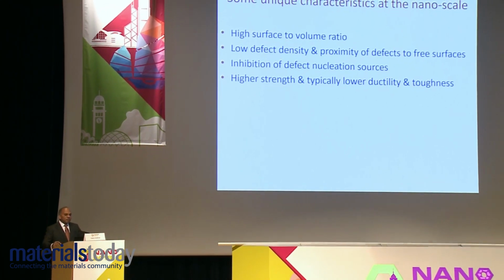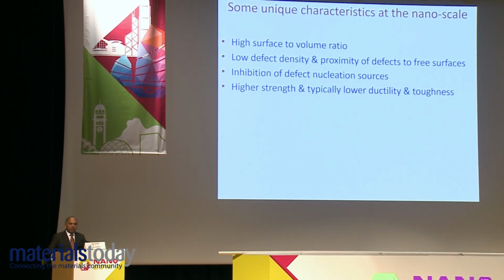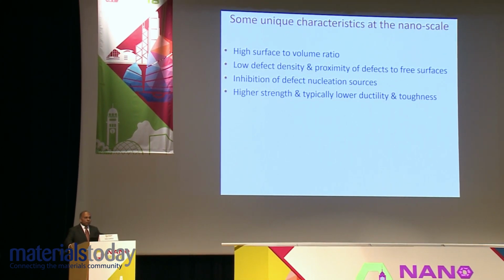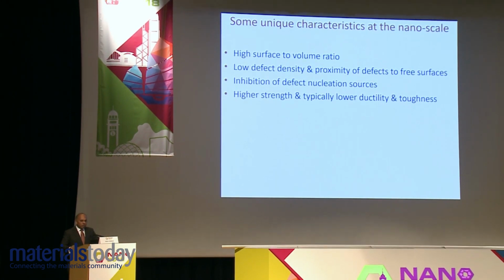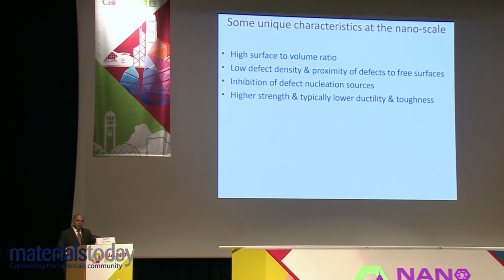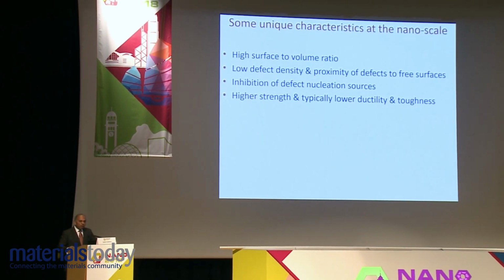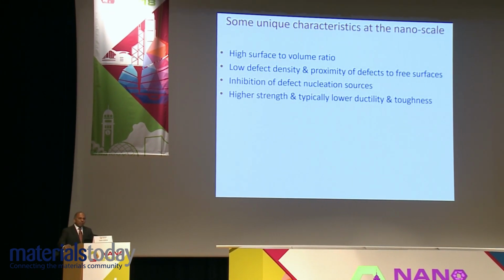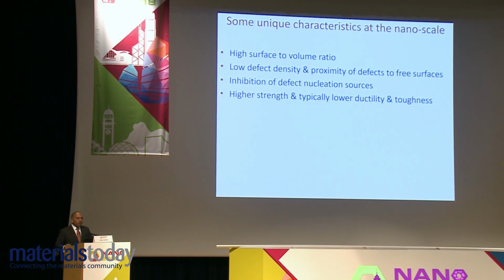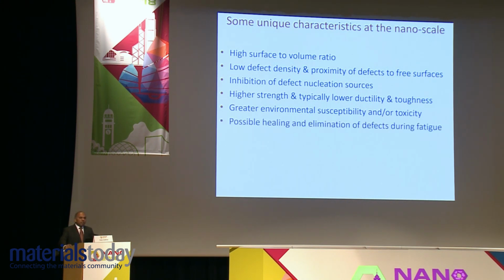typically with decreasing grain size, very rapid increase in strength through Hall-Petch type mechanisms, and of course as the grain size approaches very small dimensions, the so-called inverse Hall-Petch relationship. Typically, increase in strength is accompanied by low ductility, toughness, damage tolerance, and resistance to fatigue crack propagation. Greater environmental susceptibility and possibly toxicity as well in some cases. But there are also some advantages of nanoscale structures.